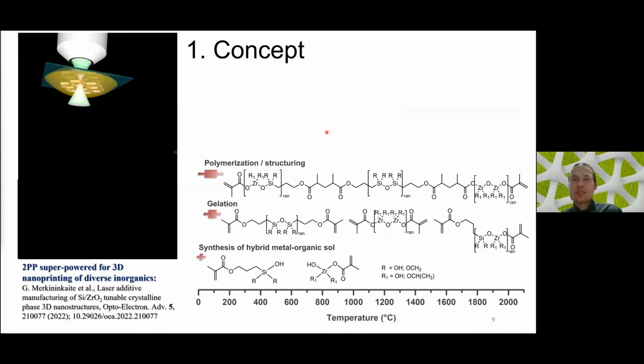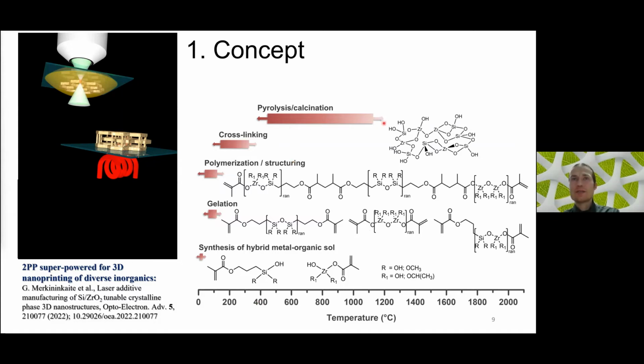Getting into more detail of what is happening and why it is so. We look at two-photon lithography, like super-powered 3D printing for diverse inorganics. Firstly, we polymerize the structure, we write it in, and then we heat it. Heat additionally induces cross-linking, so some further polymerization and densification of the material can occur during this initial heating, at hundreds of degrees Celsius. But if we go to higher temperatures, the organic constituents such as carbon and hydrogen are evaporated, and the inorganic ones remain, forming ceramic or glassy substances, depending on the initial material, like silicon, zirconia, or some other oxides.